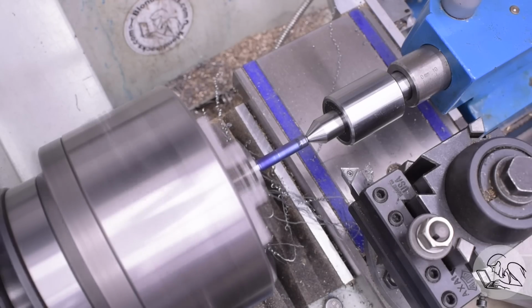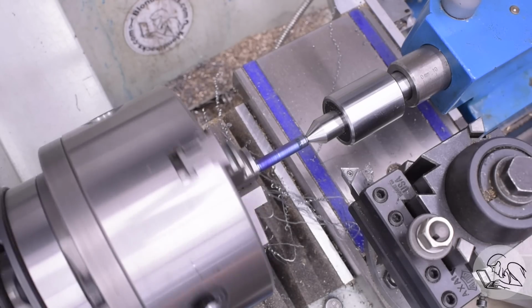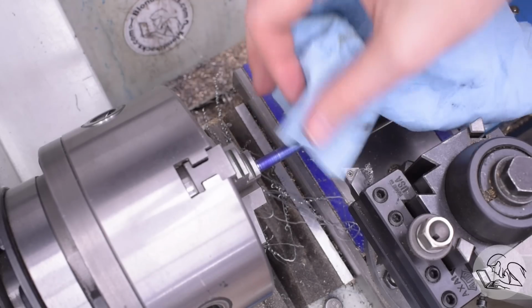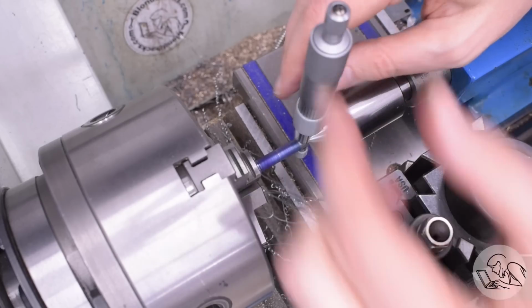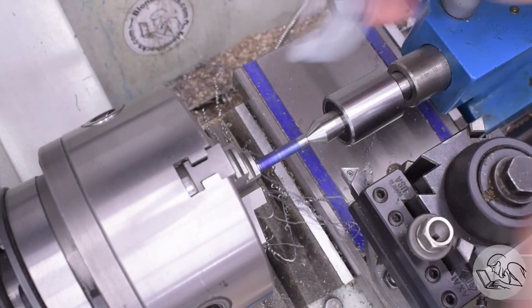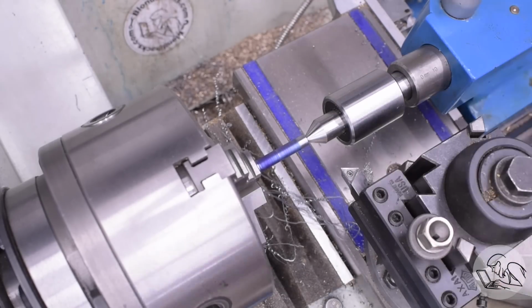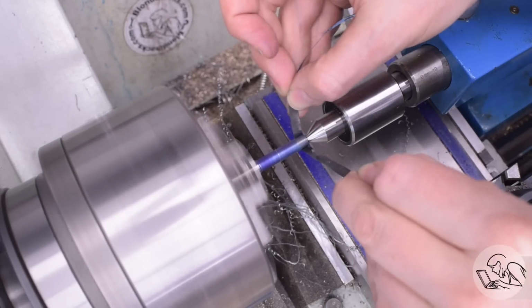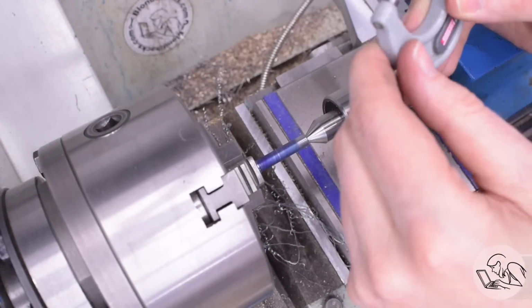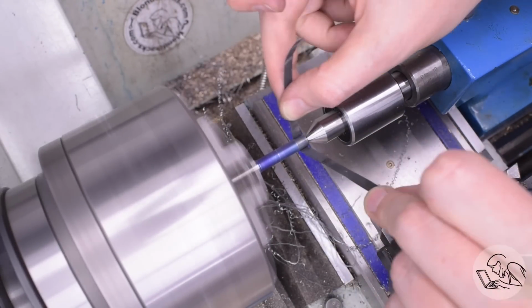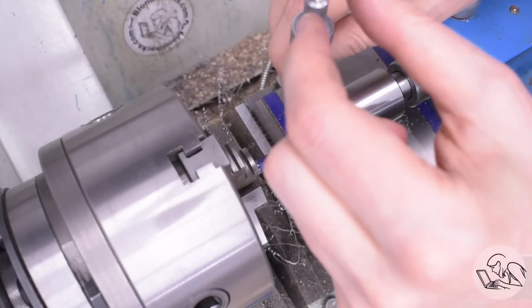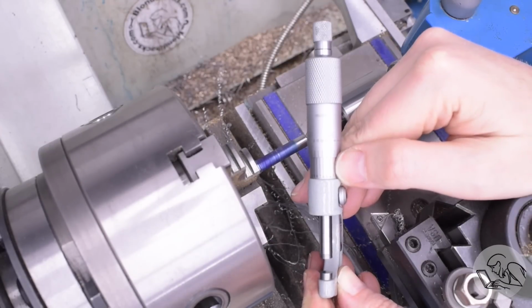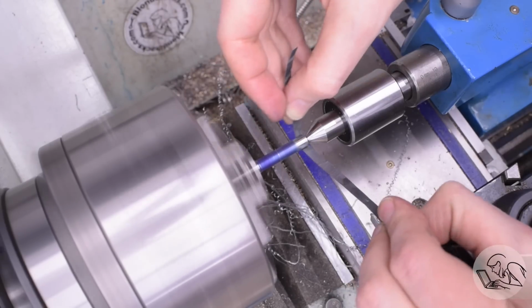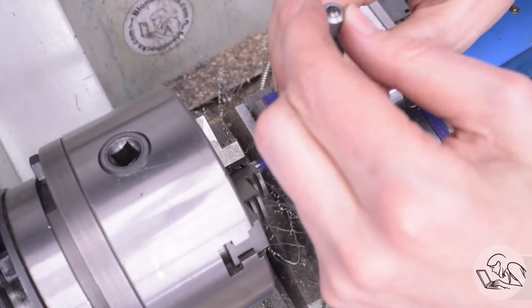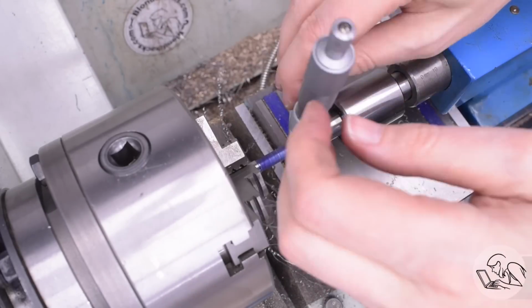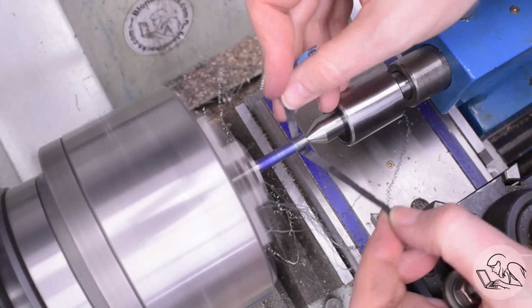I use 320 grit emery for this, and I use it with cutting oil, which helps keep the sandpaper from clogging up, which makes it last longer. However, that does slow down the cutting action. The rule of thumb is using emery with cutting oil roughly doubles the grit. So my 320 becomes 640 grit. So it cuts slower, but because the paper doesn't clog up, you can use the same piece of paper for a long period. If you use it dry, the paper clogs up instantly and you go through a lot of it. So I'm not sure that it's actually faster to use it dry, even though the grit is lower.